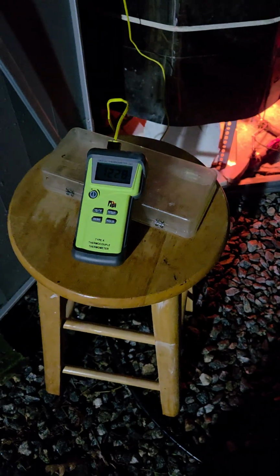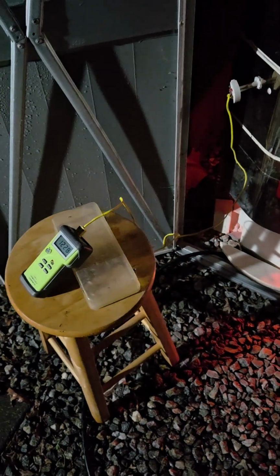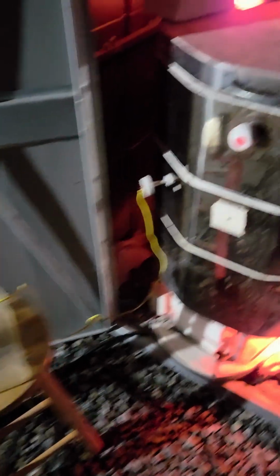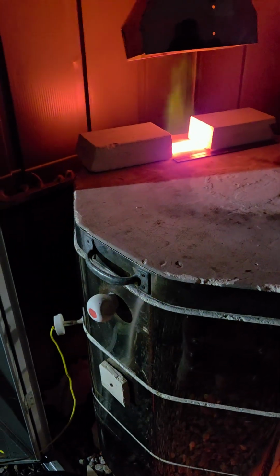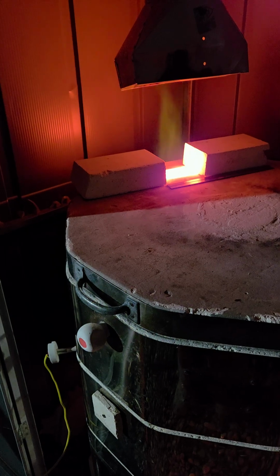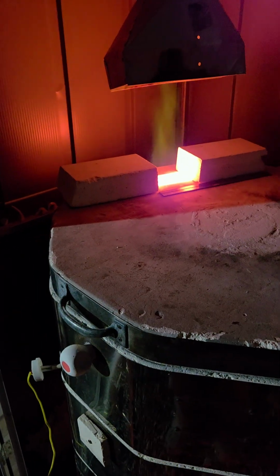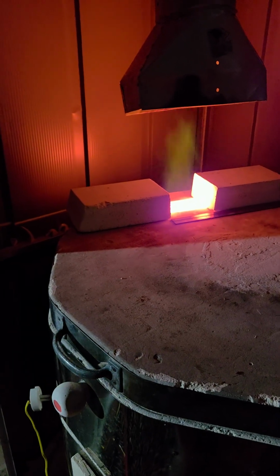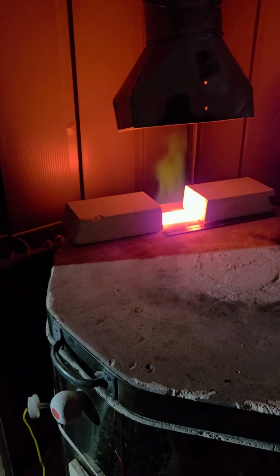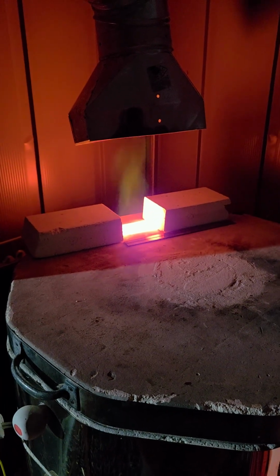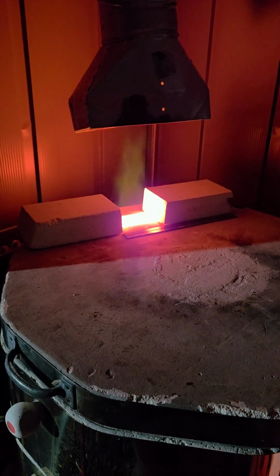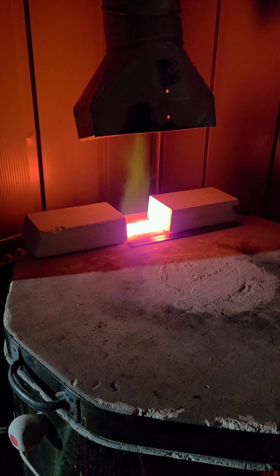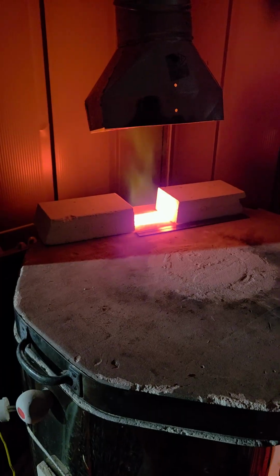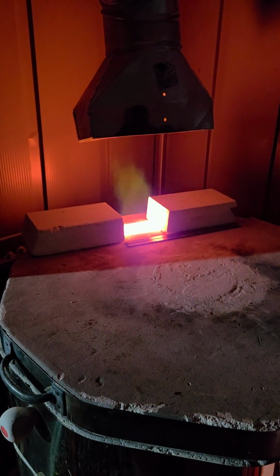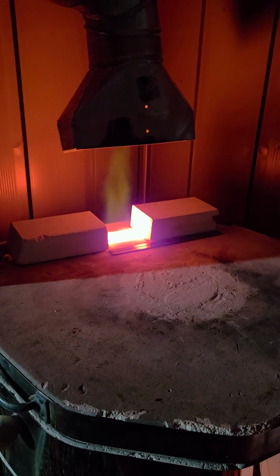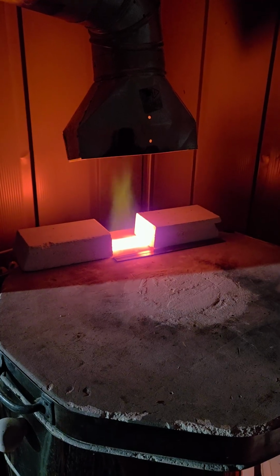So I'm at 1228 degrees, and I did about a 5-minute temperature climb rate check, and it was showing 73 degrees per hour, which is a little high. As I mentioned, I'd like to see 60, so I went ahead and turned the gas down to 2.1. The reduction flame is still good, and it seems to have stabilized. I'll do another 5 or 6 minute temperature climb rate check, and then decide what I want to do. I would like it not to go too fast at the end. I really do like the last 100 degrees averaging only 60 degrees per hour.